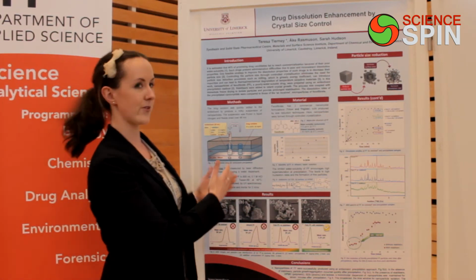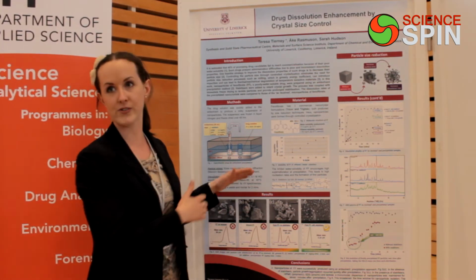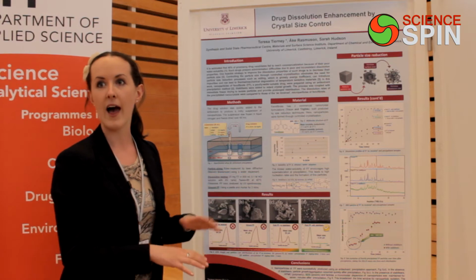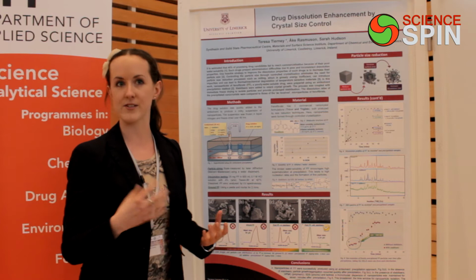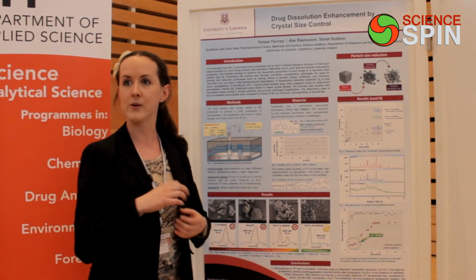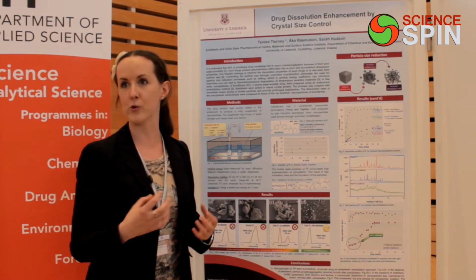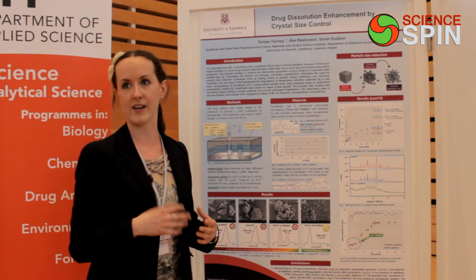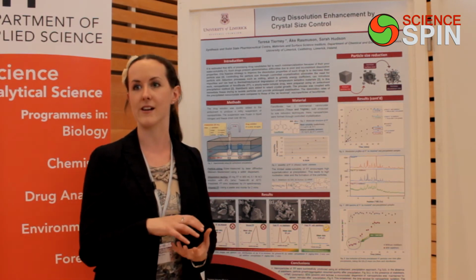I use a method where I inject a drug solution into a water solution where it's poorly soluble, and this causes the drug to precipitate as tiny little particles. These have a tendency to grow, so I incorporate some growth inhibitors, which bind to the surface and stop more growth units from joining on, hindering the growth process. So I'm trying to maintain the tiny little nanoparticles.